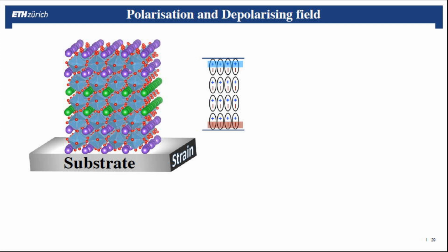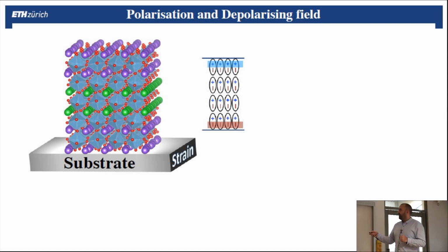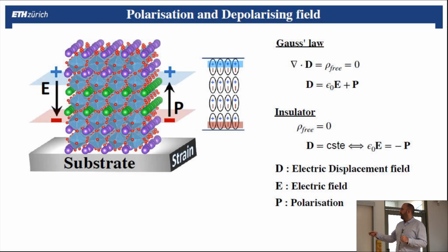Let's now assume that the green one here is a ferroelectric material, which means that you have alignments of dipoles like this, which will result, if this is non-ferroelectric, non-polar, to a discontinuity here at the interface. So what happens is that this alignment of dipoles will result at this interface of net charges, plus here and minus here. And this will create depolarization, but it's also a problem because it brings a discontinuity of this material. This is due to the Gauss law.